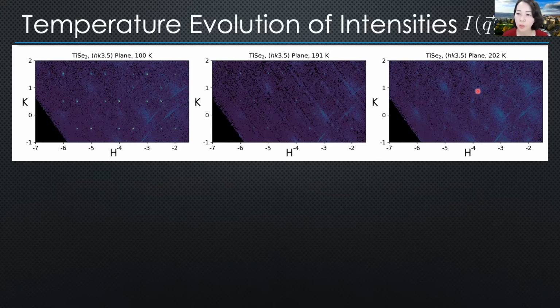At high temperature, you have kind of blurry data. But then as you lower the temperature, you start to see some peaks show up. And this is a plane without the lattice Bragg peak. That's why it's all blurry at high temperature. And then you further lower the temperature, you see the sharpening of these peaks. This is a superlattice peak because it's in a plane where there is no Bragg peak. Half plane, right here, a half plane.